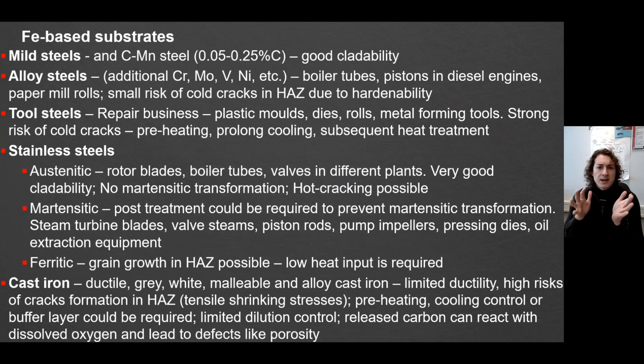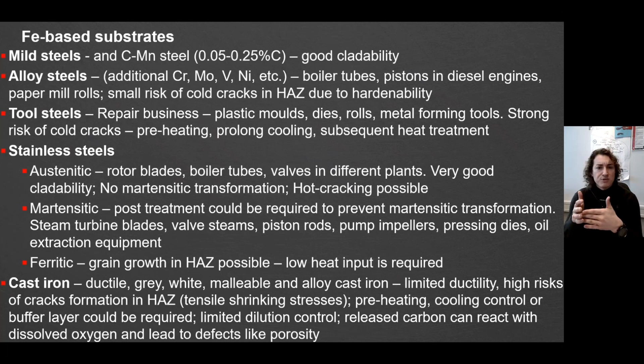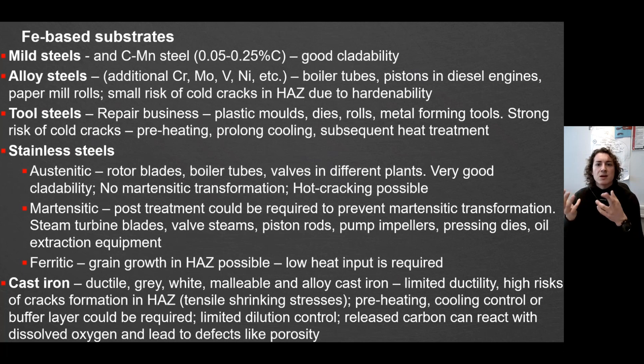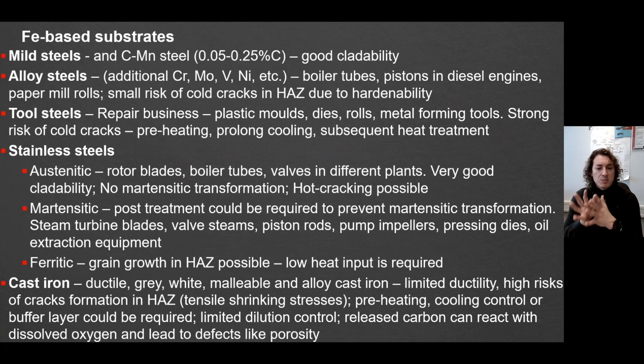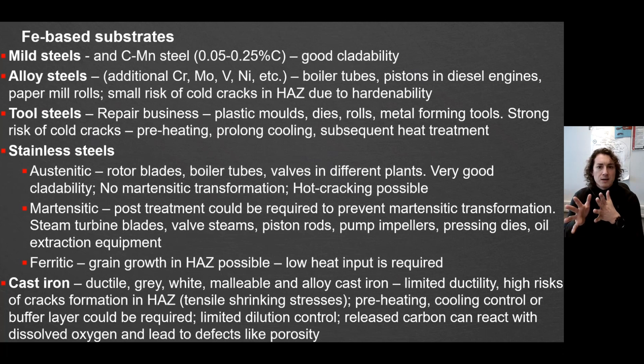The final group is cast iron. Cast iron is generally a very critical material to work with. What we have learned is that if you work with EHLA or a high-speed process, you can avoid a lot of interaction with the substrate and a lot of diffusion, and many materials can be directly applied to cast iron. In most cases in laser cladding, based on my experience, you work with extreme preheating or buffering, especially if it goes in the direction of repair.